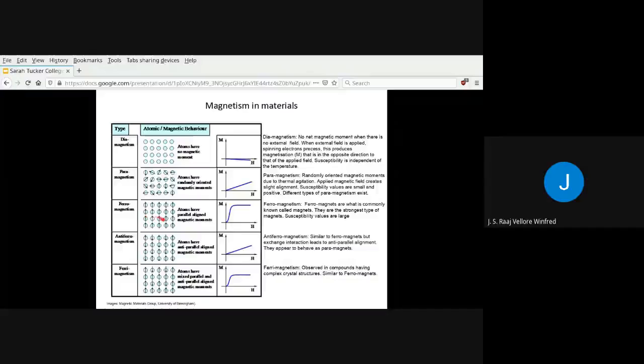Ferromagnetism is what we normally see in day-to-day life. For example, your daily magnets that you come across are all ferromagnets. What distinguishes ferromagnets from the other two that I just mentioned is that the magnetic moments of the atoms here are perfectly aligned, and they are parallel to each other. So this means that any small application of your external field would result in a large magnetization of the sample. That's the reason why you see a very steep curve over here. And afterwards, of course, the magnetization saturates because all the atoms are perfectly aligned. And the susceptibility values for ferromagnets are very large.